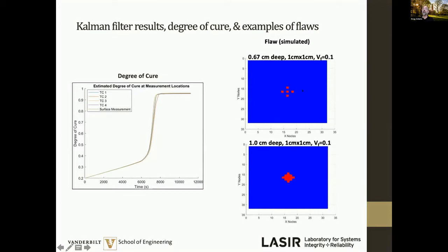But in terms of flaws, what I'm showing here on the right is the ability to detect flaws at different depths in the material. So this is at 1 centimeter deep. These are both 1 centimeter by 1 centimeter volumes that occur beneath the surface. And you can see here, this is closer to the surface up top. This is deeper beneath the surface. And essentially what we're doing is we're simulating flaws using a 10% volume fraction of fiber to simulate the possibility that you have more or less resin in those pockets. And you can see that even as you get deeper, we're able to see the flaw and we're able to see those temperature variations that would potentially produce, as I showed you earlier, flaws in this material.